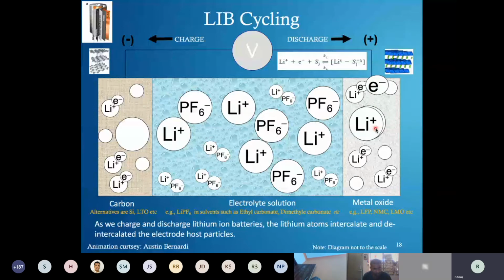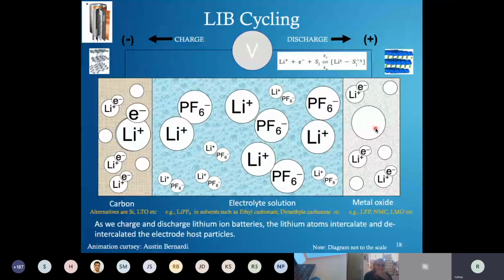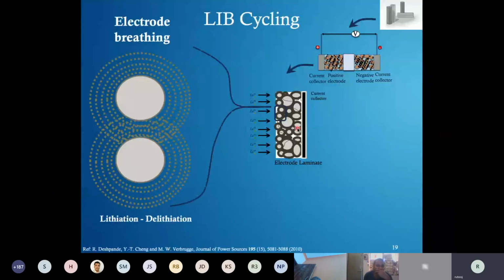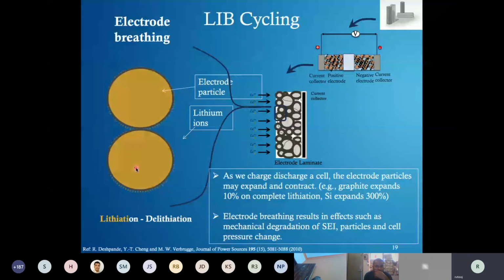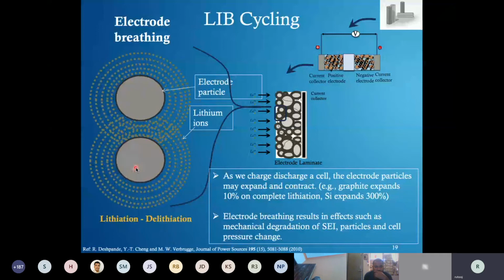Now, whenever a host particle gets an additional lithium atom, the thing that will happen is, whenever you lithiate your electrodes, so assume that these circles are electrode particles and these are lithium ions, when you start intercalation, you would see that your particles are expanding, and when you deintercalate, your particles are contracting. The color change is also there in certain cases, but that's not of reference here. So as we charge and discharge our cell, lithium ions go inside the electrode particles. The electrode particles may expand, and when you deintercalate from those particles, they will contract back.